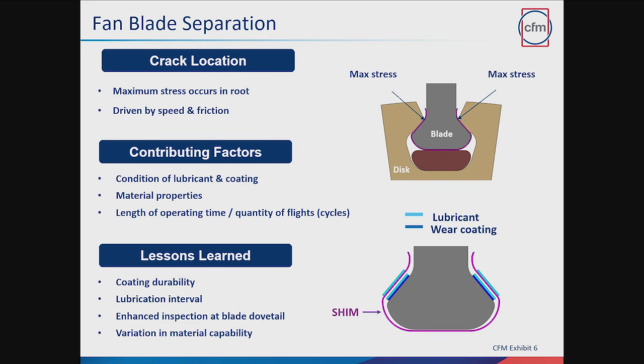After our observations of the early fleet engines, we added two things. We put a shim in place, which is just a thin sheet metal piece that goes along the length of the dovetail, and it protects the blade and disc from each other, as well as reduces friction. To further reduce friction, we now put a lubricant on, and the requirement was every 3,000 cycles you had to take the blades out and re-lube them or reapply the lubricant. That was all in an effort to reduce the friction level.